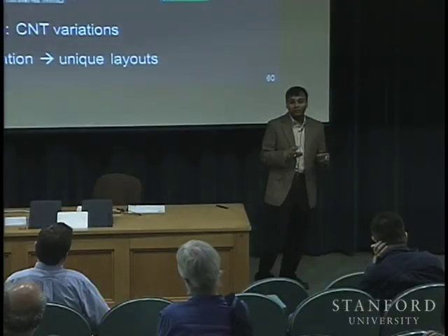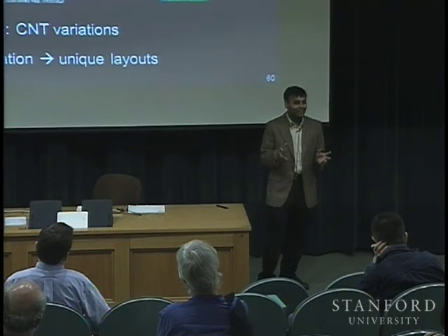Now with this multiple transfer technique that this undergraduate student has developed here at Stanford, he has been able to show that up to maybe 5 transfers or more, he can keep increasing the density of the nanotubes. Remember, increasing density is not good enough, because oftentimes people have shown us density increasing but the on currents do not increase because of weird interactions between the carbon nanotubes. So it's very important that when you increase density, the on currents actually increase. With the undergraduate work published in Nano Letters, he could show that the on currents would increase linearly, which was really great.